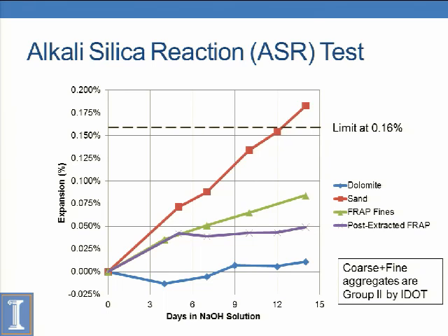And then the sand, which consisted of quartz, which is silica, and dolomite. We can see that it was a little bit above the limit. This is IDOT's limit for expansion. So with this scenario, with a slightly expansive sand and non-reactive coarse aggregate, it meets Group 2 by IDOT, which pretty much says as long as the mix contains slag or fly ash or uses a low alkali cement, ASR should not be an issue. So in the end, the big conclusion here is that FRAP is not an issue with ASR, provided that it's a non-reactive aggregate base like dolomite.